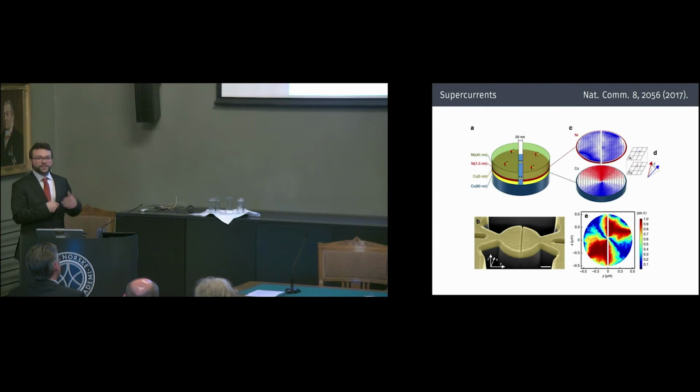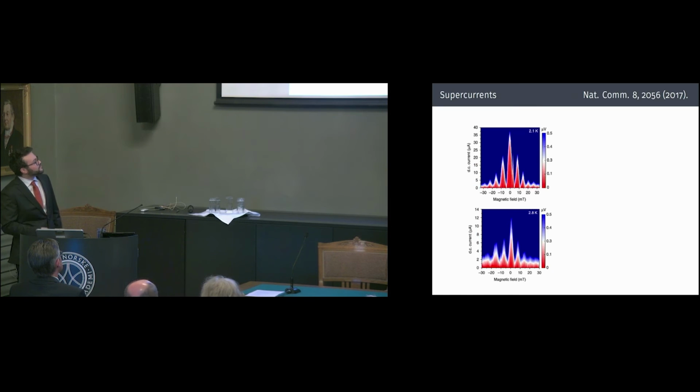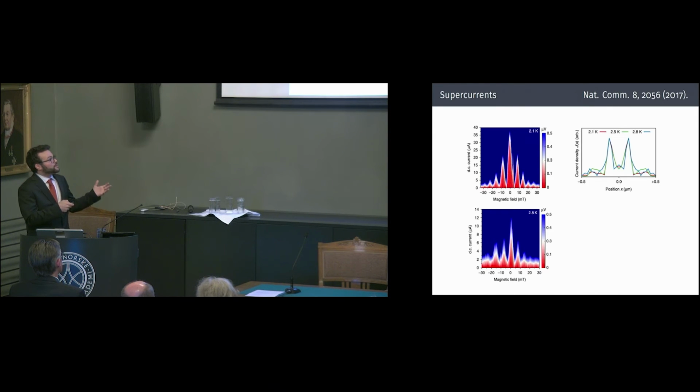And this means that you can learn a lot about how superconductivity interfaces with magnetism in this kind of device by basically studying the current flowing down here and up here between the two halves of the superconductor. So in their experiment, they then did something called a quantum interference experiment, where they basically checked the electric current flowing between the two halves of the superconductor as a function of an applied magnetic field, which gave some figures that looked like this. Then we helped them associate this to theory and find out basically exactly where in their system the supercurrents would have to flow, which is, here's the spatial distribution we found, in order to produce the observed interference experiments.